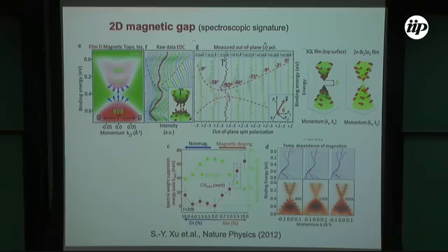So what we found is that if you dope them with magnetic impurities, so this is an example of that, and then measure the spin texture near the band edge, where it looks like there is a gap. We see that if you have a Dirac cone in the undoped topological insulator, the spin texture is like that. I showed a few scans of that. But here, even if you have states here, the spin texture is different.